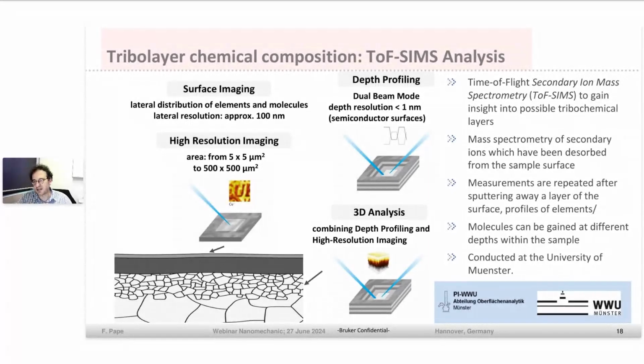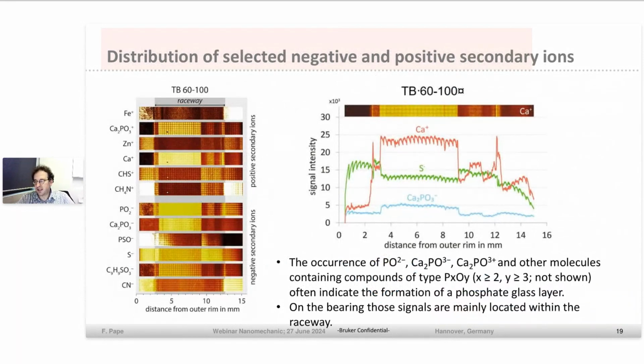For the TOF-SIMS measurement, just short, here we have the surface imaging to investigate the lateral distribution of elements and molecules on the surface. This is done with a mass spectrometry measurement of the secondary ions which have been desorbed from the sample surface in the spectrometer itself. And we can also do some depth profiling. In this, we sputter away some amount of the surface in the range of a few 10 or 100 nanometers, and then repeat our measurement again. In doing so, we can achieve the distribution of the elements on the surface and also in the depth.